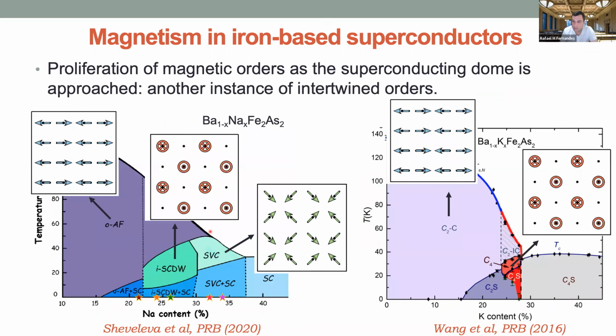And that is actually what they see in some compounds, in some hole-doped compounds, as they start approaching optimal doping, they see the appearance of these other phases, as I'm showing here. This is another instance of intertwined orders. You have three different magnetic ground states that, however, come from the very same mechanism.